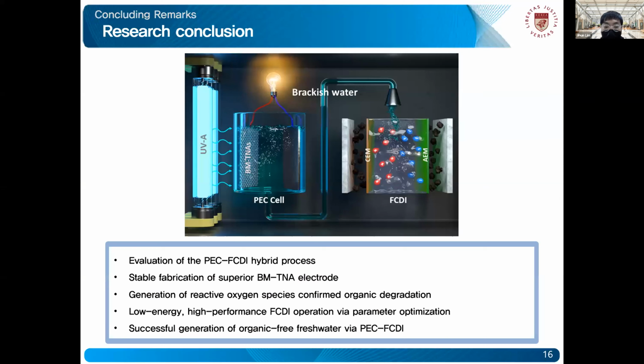Now, conclusively, in this study, evaluation of the PEC-FCDI hybrid process was conducted, and a stable fabrication of the superior BMTNA electrode was confirmed. And also, during the PEC system, generation of reactive oxygen species was confirmed, which led to the organic degradation of the model organic pollutants. Also, in the FCDI system, low energy, high performance operation was analyzed via the optimization of the two key operational parameters. And through using this hybrid process, we generated the organic-free freshwater that met the freshwater TDS standards, and we confirmed the feasibility of this PEC-FCDI hybrid process.